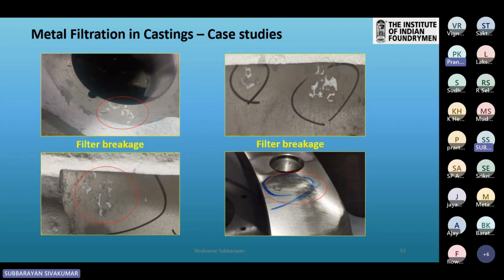I have some case studies from my experience, showing to what extent the filter helps to filter out the inclusions. If it is not designed or deployed properly, it creates a problem also. Here are some actual casting pictures post machining. A silicon carbide filter was used and it broke and entered the casting. Post machining, it was revealed like this and we lost the casting.